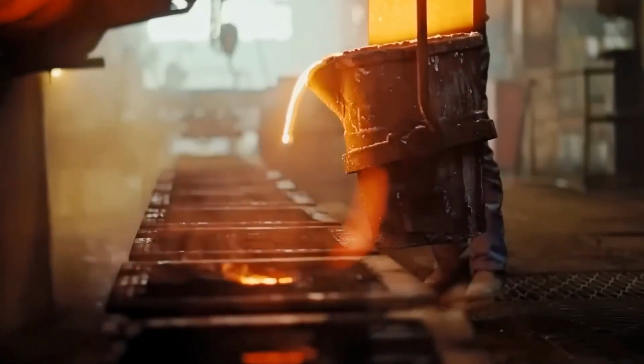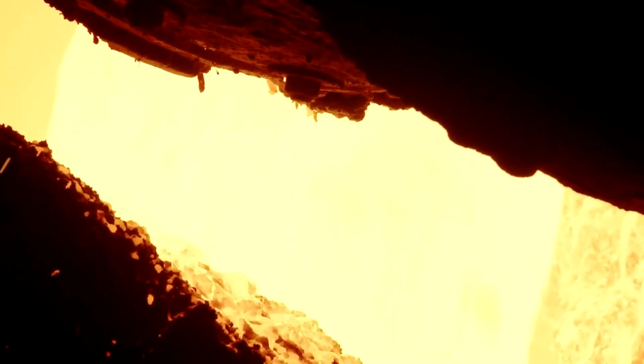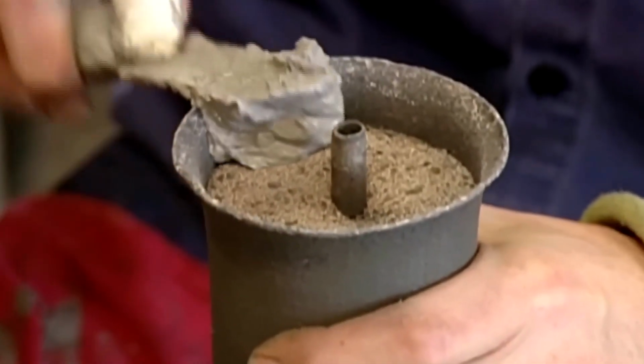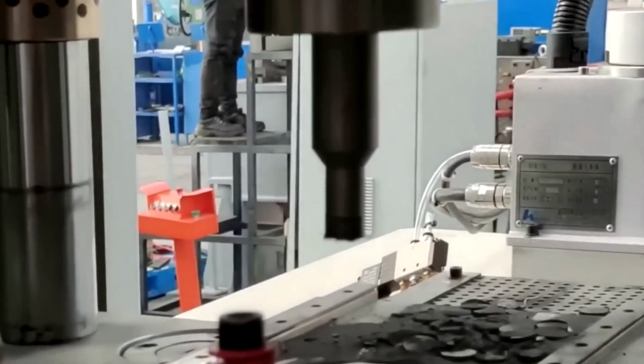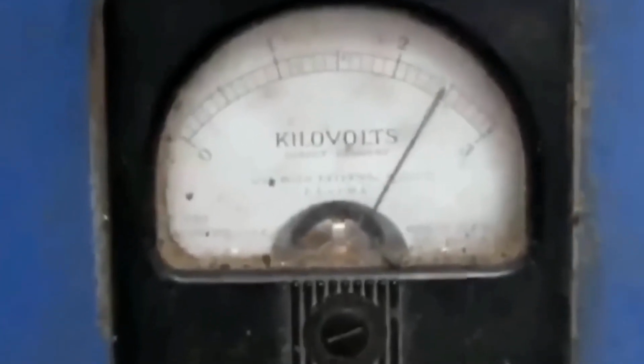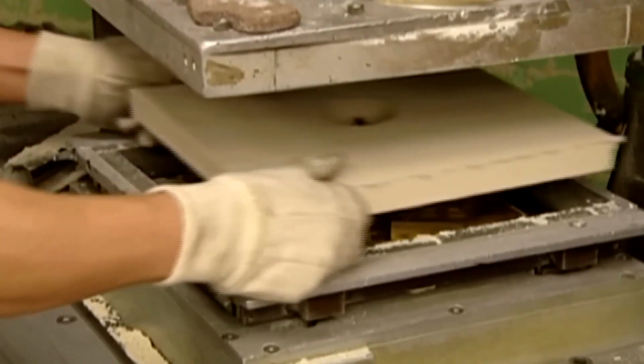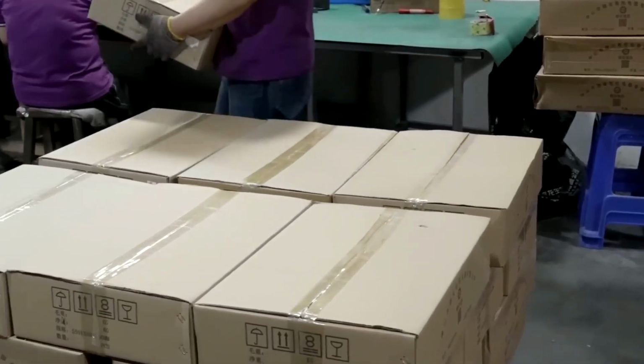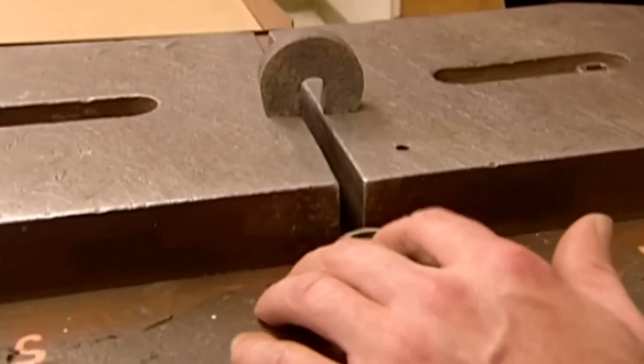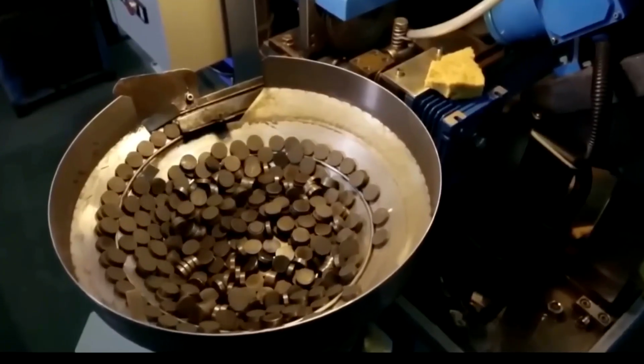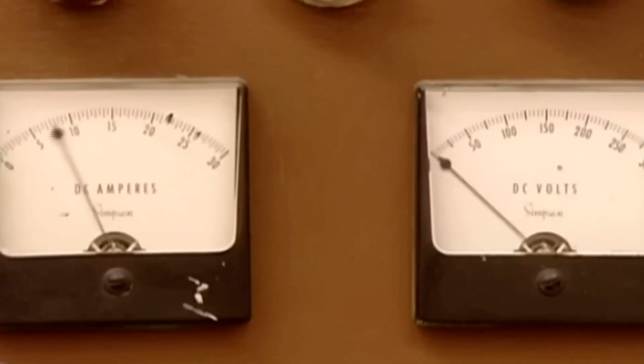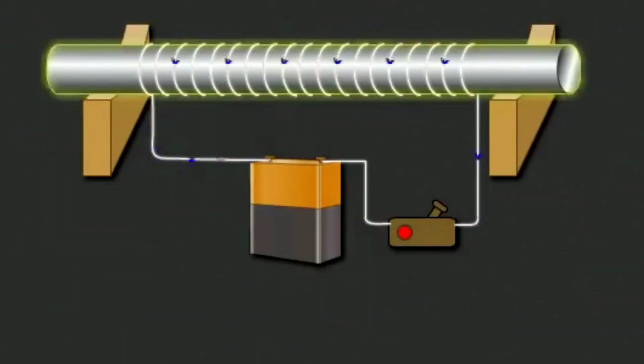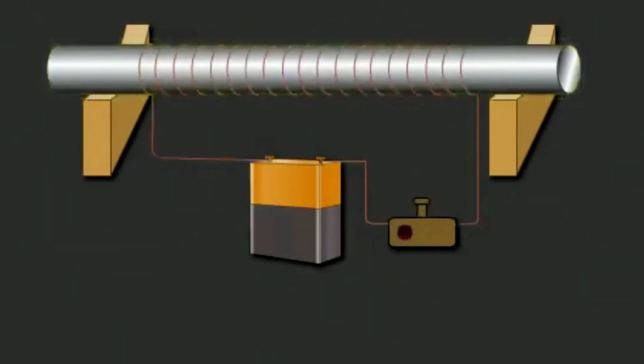These freshly pressed alloy blocks are deceptive. Though they appear solid, they are as brittle as ceramics and possess no magnetic properties at all. To awaken them, they are placed inside a sealed furnace, once again completely isolated from the outside air. Inside the chamber, the temperature gradually rises to between 2,200 and 2,400 degrees Fahrenheit, just hot enough for the surfaces of the powder particles to begin fusing together.